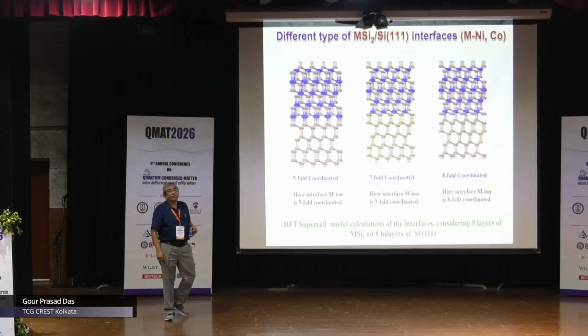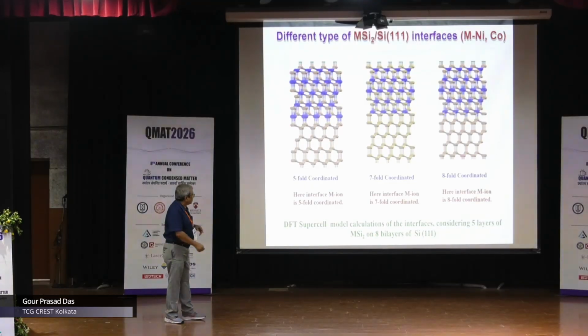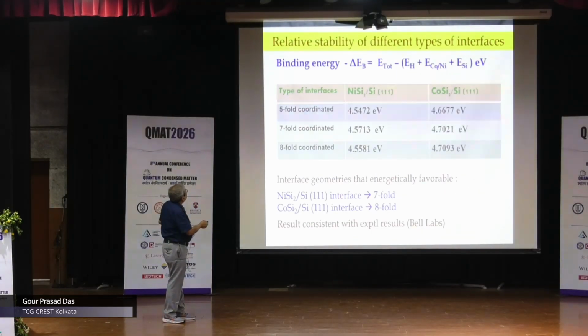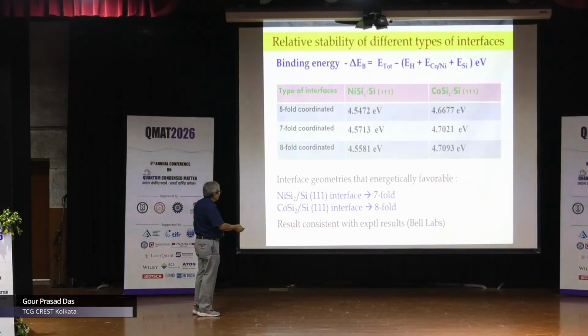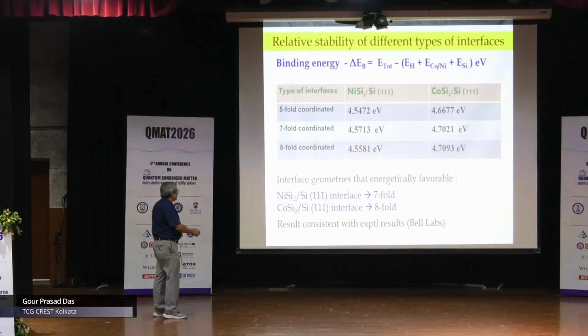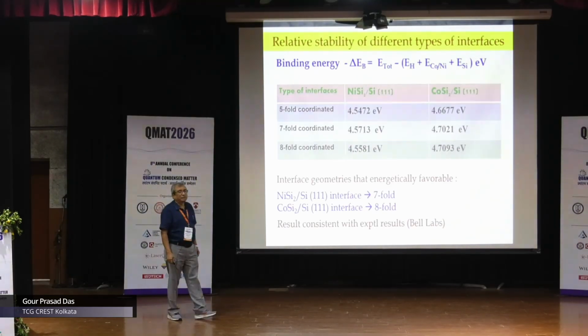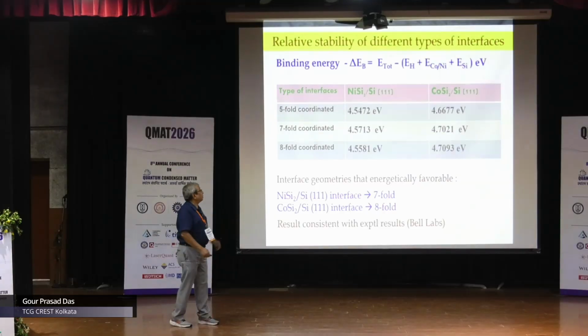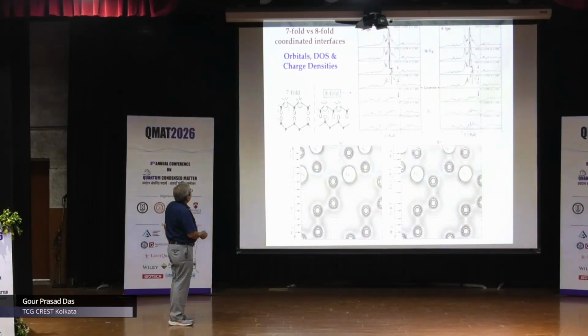It was done in Hamburg, okay, in those days, and we found, interestingly, that nickel disilicide silicon and cobalt disilicide silicon, both we saw, and we came to the conclusion that nickel disilicide silicon is 7-fold coordinated and cobalt disilicide silicon is 8-fold coordinated. And this result was consistent with the experimental result which was obtained by Raymond Tung in Bell Labs in those days. Okay, so again, here is a matter of details.